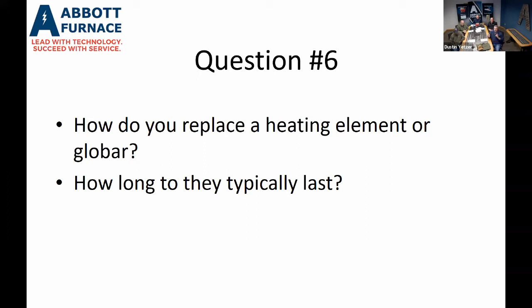A couple things, there's a distinction between the heating element and glow bar. Heating elements are usually what you see in the preheat. They're wire wound, usually on a support tube. Those are supplied in your preheats, and then your high heats are what they call glow bars, which have silicon carbide heating elements, or heating tubes, inside. That's called a glow bar. Typically your glow bars are higher temperature. You won't see heating elements typically over 1800 degrees, because they start to sag too much above that temperature.